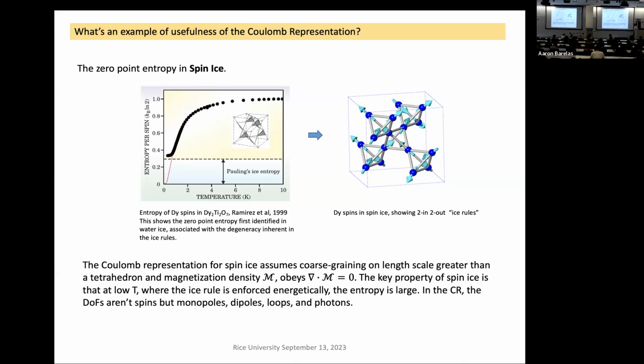So the Coulomb representation for spin ice assumes coarse graining on length scales greater than the tetrahedron, and the magnetization density then equals 0. The key property of spin ice is that at low T, where the ice rules are enforced energetically, the entropy is finite. In the Coulomb representation, the degrees of freedom aren't spins but monopoles, dipoles, loops, and photons.